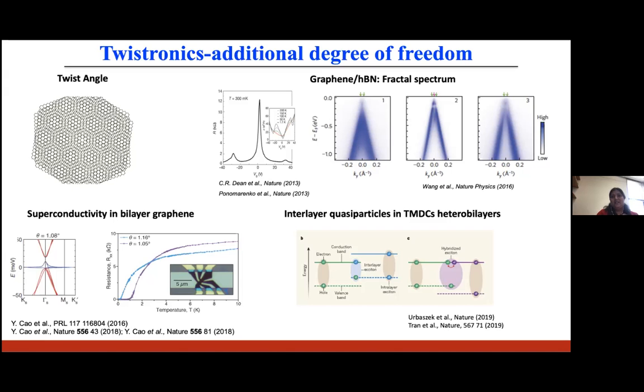And what happens is that the electron in such a heterostructure can no longer move freely in the planes of these atomic layers, but is trapped in the spatially periodic potential energy variations of this Moiré potential. And so we have seen recently a body of work where first it was shown that by just stacking graphene on HBN, it can generate these secondary Dirac cones. And as a result, in the transport measurement, you can see